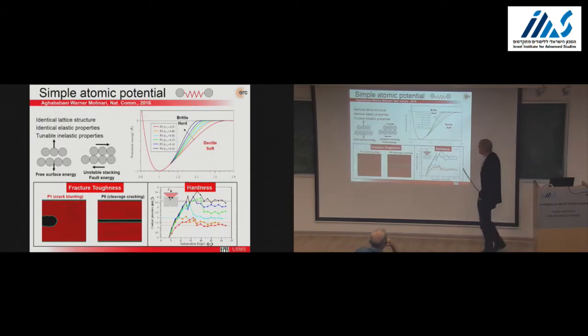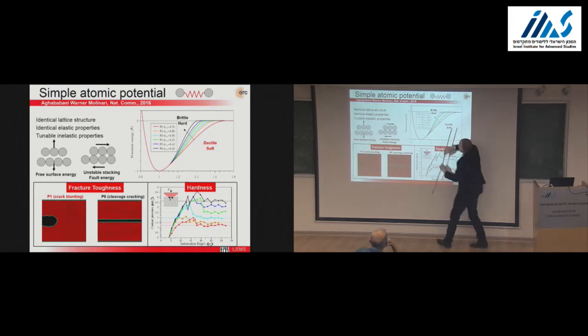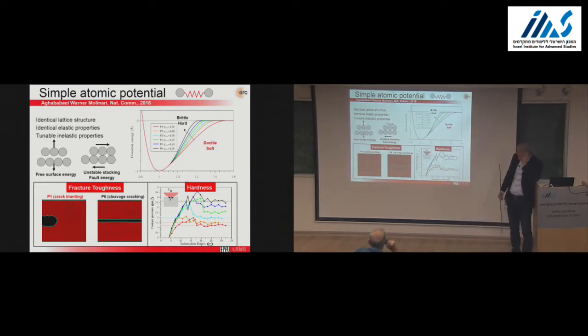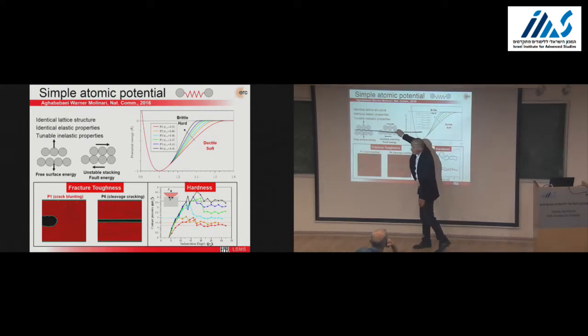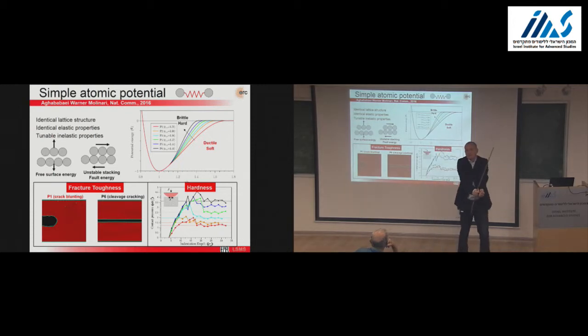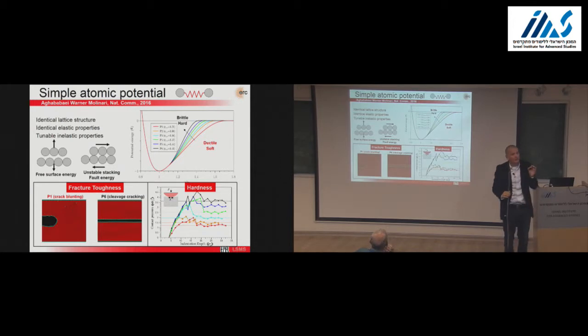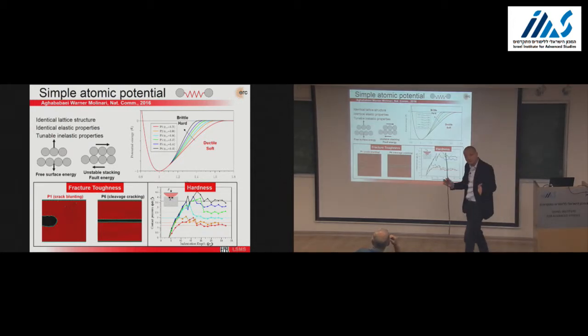So this is our potential family. It's a very simple pair potential, repulsive tail, attractive tail. We can play with this tail to change the ductility and brittleness of our material. And we control two things: the free surface energy and the unstable stacking fault energy, which is going to control the ease of getting ductility and plasticity in our system. You can see we have a good control of the hardness when we do indentation tests with this potential family. We do not change the tail right at the origin. We only change it at 10% stretch, so that we don't vary everything when we change the ductility. We want to keep the elastic constants, shear modulus, and Young's modulus constant within a range of deformations where we can hope to understand something.